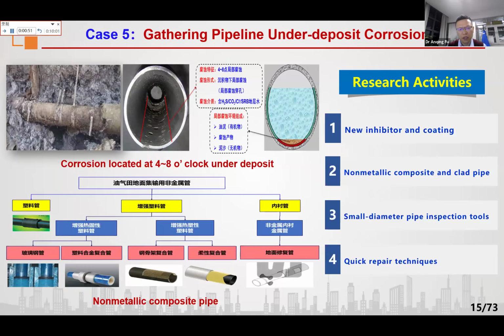Since this kind of material has no corrosion, but there is still some degradation, especially at temperatures over 80 degrees C. It can cause a big issue. Another disadvantage of the non-metallic pipe is that the connection joint is a big issue. Since we usually use many kinds of joints, there are a lot of leakages due to the material going inside. And another thing I want to say is that small diameter pipe inspection technology and quick repair techniques under high temperature, high pressure are still big issues in the field.